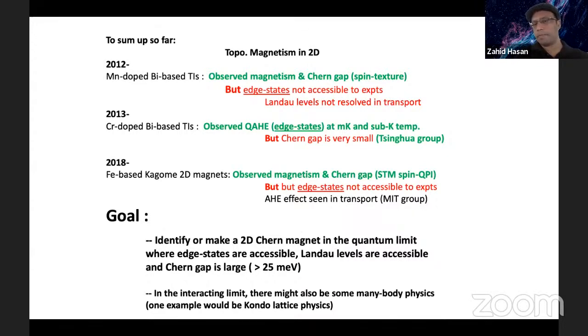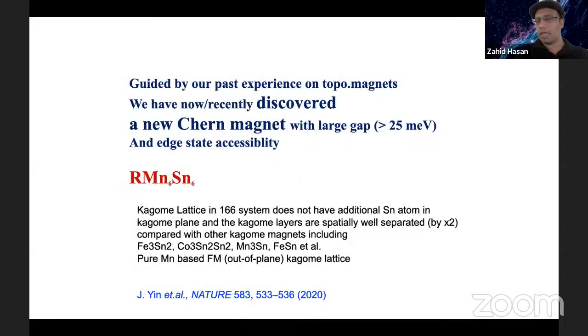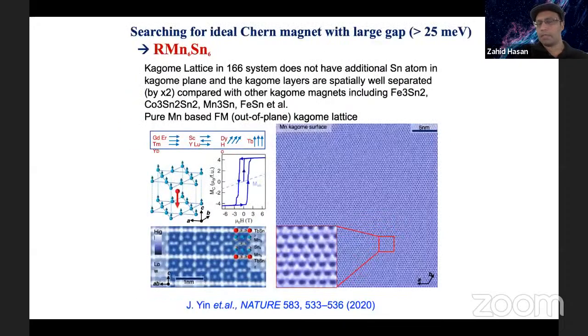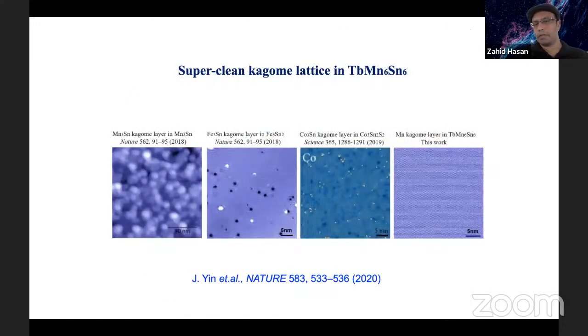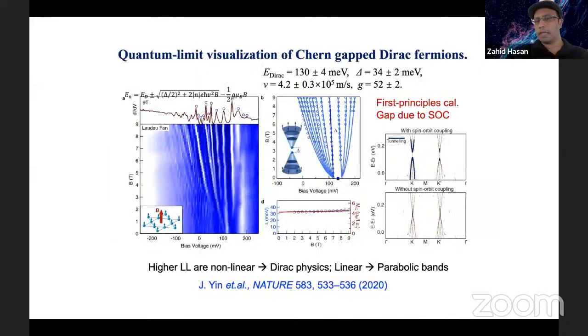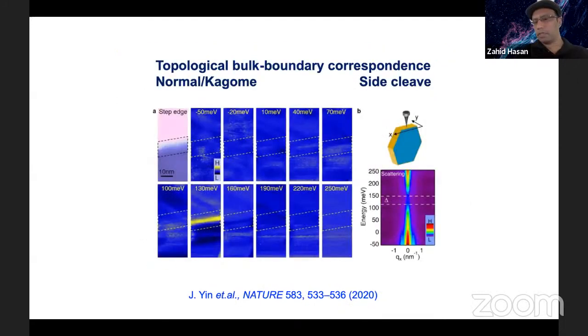The larger the topological gap, the more robust the edge state. And it's not just from a device point of view, it's also fundamental. You can do more fundamental physics out of it. So one obstacle is to find a clean material that has a large gap. And this is what I described, that this compound is very clean compared to the pre-existing compounds. We cannot even see a defect in my STM field. And it has a large gap, 34 millivolts.